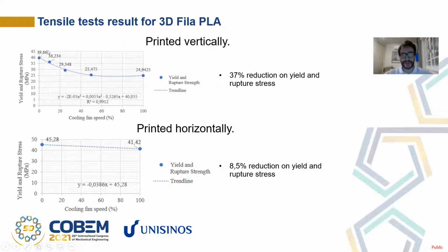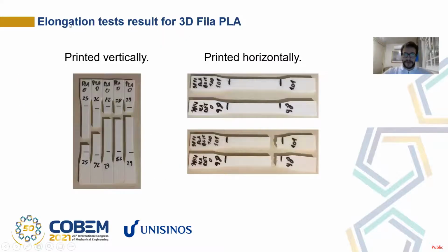We can also see here that I chose to test this region a little bit more, because it is the most interesting, where the drop really happens before stabilizing here. And for the ones printed horizontally, as the reduction is quite small, I chose to just test them with the cooling fan turned off and on maximum. For the elongation, there was no difference between them. The ones printed vertically broke in the layer lines, and the ones printed horizontally broke clean and without any elongation.